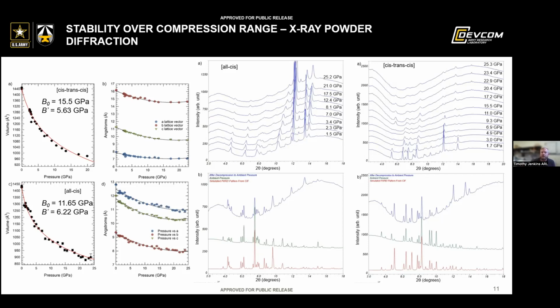with increasing pressure. So looking at the cis-trans cis, you can notice that quite quickly when we increase pressure, we start to get a very large pressure broadening, and this becomes difficult to refine at very high pressures, in that above 20 GPa, it's tricky to fit these into a refinable volume change. But converse that with the all cis structure, which has much less broadening of the peaks with increasing pressure, indicating that we're not developing the material failure on the macro scale that we are with the cis-trans cis arrangement.